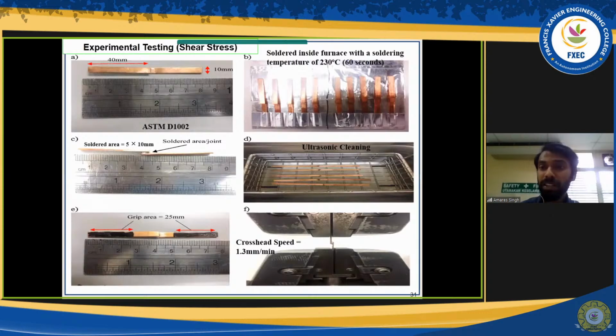As for the shear strength, I'm using the ASTM standard D1002. That is the standard for soft alloys, solder alloys, soft metals. Those are the standard testing methods. So I soldered it again at 230 degrees because we want to see the relationship. We can't be using a different temperature for the wetting and the soldering, of course. So I'll be using 230 degrees Celsius to accommodate the shear strength. We'll be using a universal tensile machine to pull the specimen. This is called a single shear lap joint. You can see that the substrates are overlapping each other, as shown in figure C.